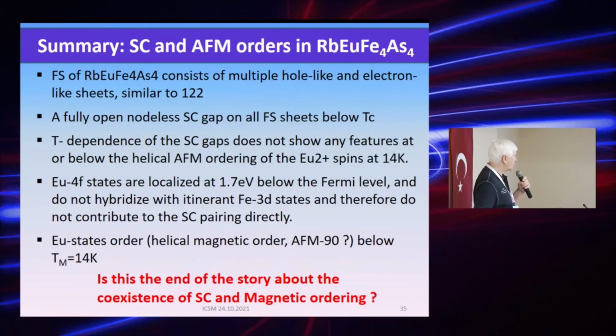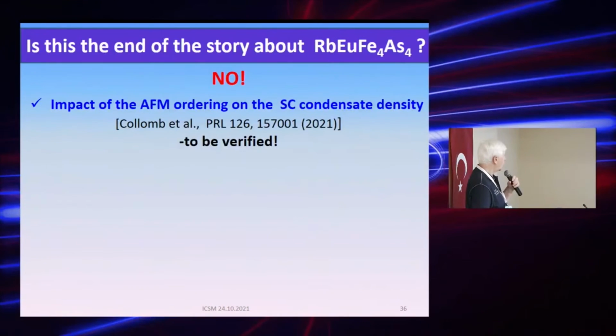So these two facts might show that this is a very trivial answer for the decoupling of superconductivity and magnetism from each other. But I don't think that this is the end of the story, because the impact of the magnetic ordering was found on the superfluid density rather than on the amplitude of the order parameter. So far, this is the only experimental data, and this for sure should be verified using different techniques. We have preliminary data that also show this happening in the system, but I don't have them ready to show.